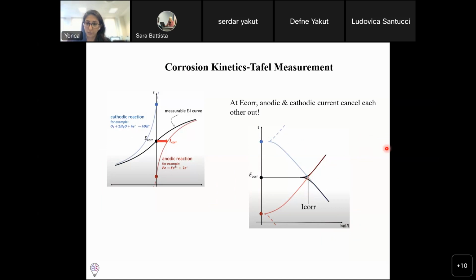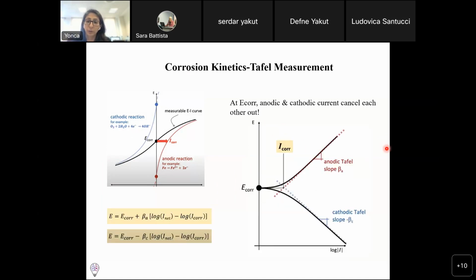And actually, this is what we need. By extrapolating these lines linearly, you can calculate the anodic and cathodic Tafel slopes, which will give you the beta A and beta C slopes. And by putting them into the necessary equations, you can calculate the net current and therefore the corrosion rates.